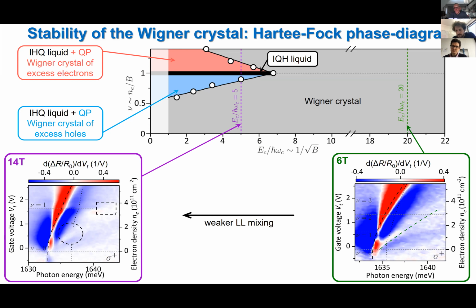So we learn now that, initially I thought that with such large values of Coulomb to cyclotron energy of 20 or so, one would not obtain fractional quantum Hall states. But we learned from Mansour Shayegan that actually up to ratios of 15, nu equals 1/3 can survive. So some of these quantum Hall states, and particularly the 1/3 state, can be very robust. So in principle, if we have a clean system, the diagram is very rich, and we will have very interesting features as we go through these liquid to solid transitions at fractions where the liquid state is very robust.